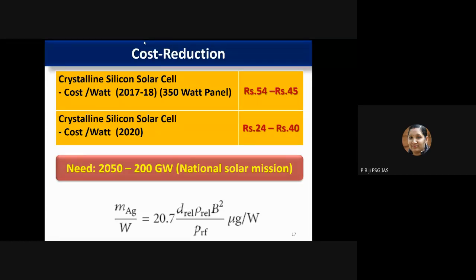If you see this equation, the mass of silver required for the front grid is inversely proportional to the denominator, which is the acceptable fractional resistive loss due to the front side metallization. Irrespective of the finger design, this equation shows that as the mass is reduced, the fractional resistive losses will increase. So somehow you should have an optimal design for the metallization pattern to reduce this: either you should go for a less silver technology, or you should go for an alternative metallization.